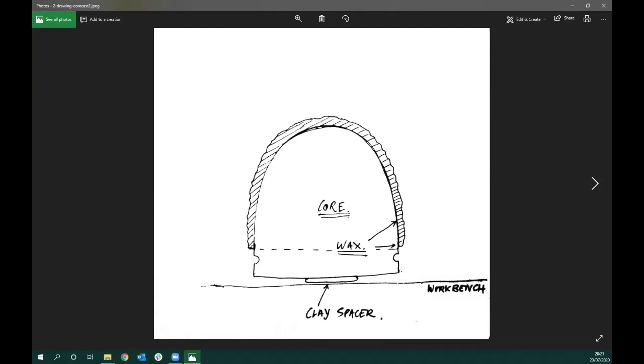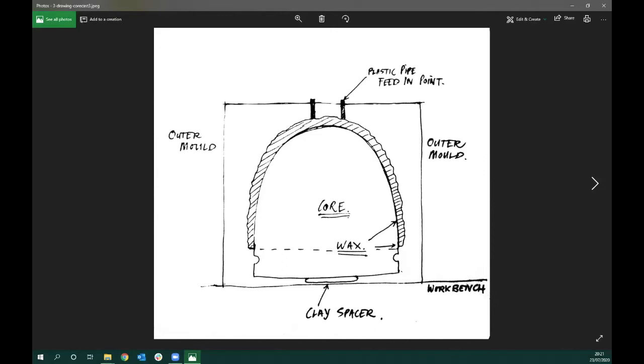So that's the wax over the top of the core, and I've built it up with about 5 or 6 layers of wax there to create a thickness of about 2 to 3 millimeters. So the next image, this shows the outer mold, which is poured in a separate casting, after we've replaced the core back onto the bench.